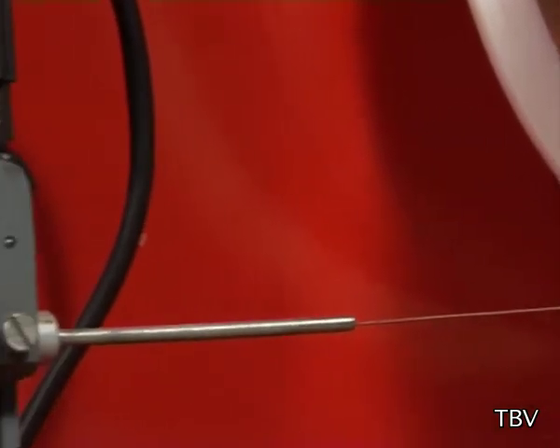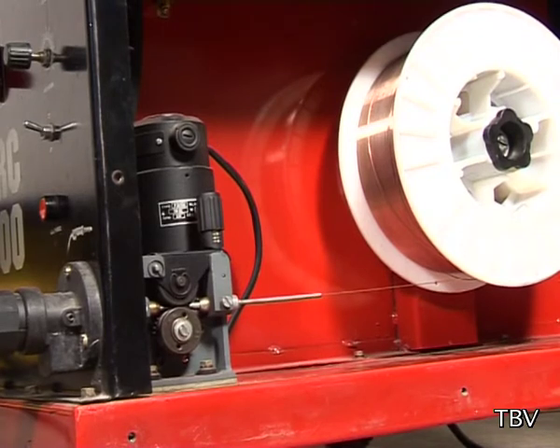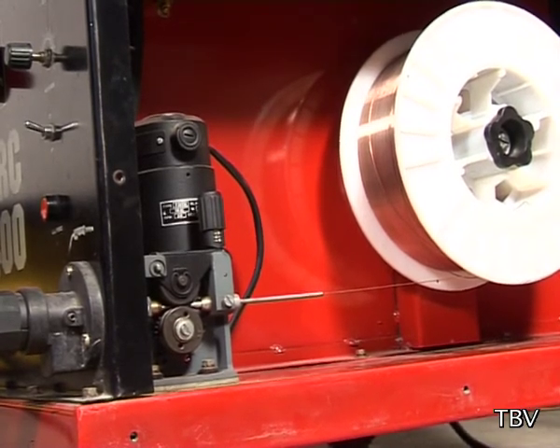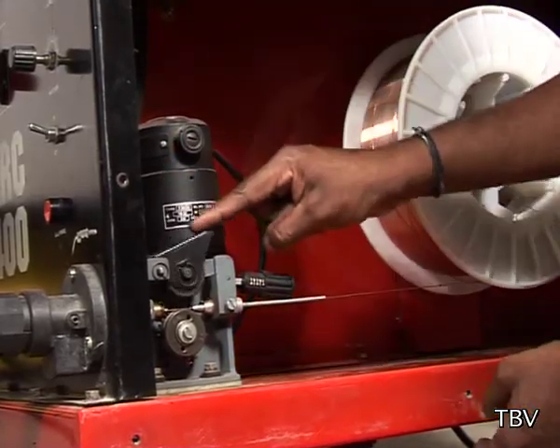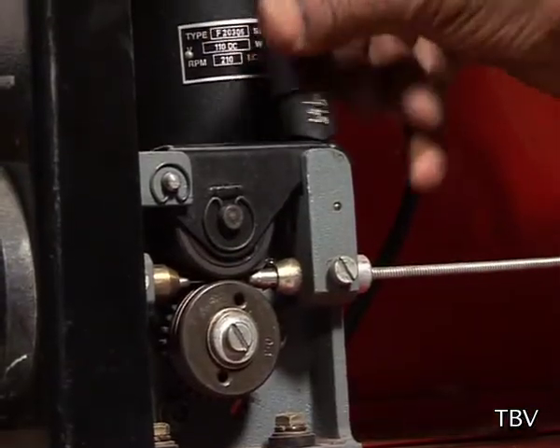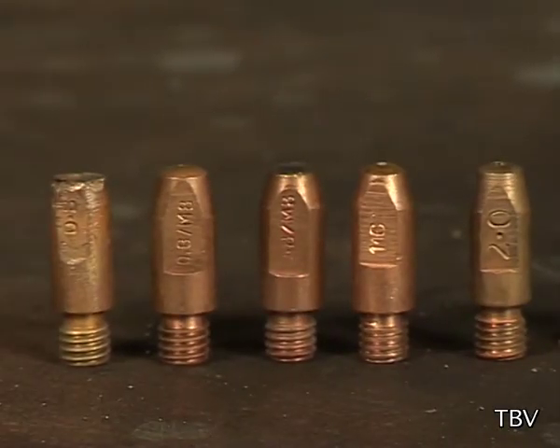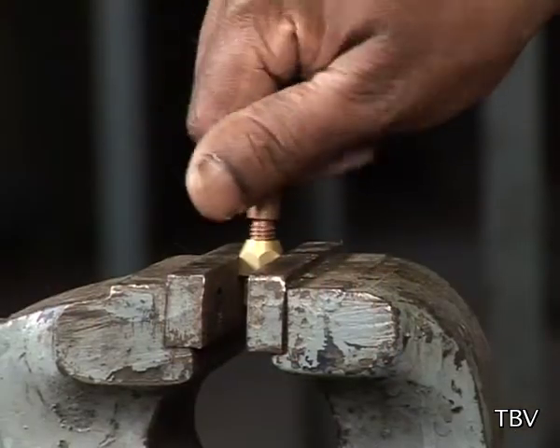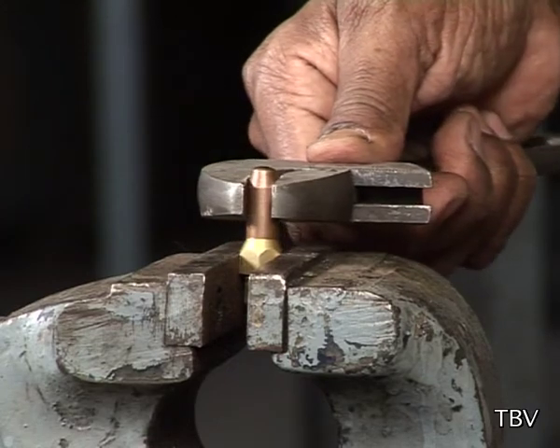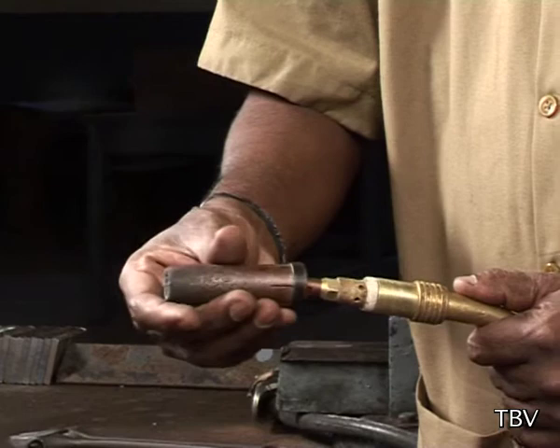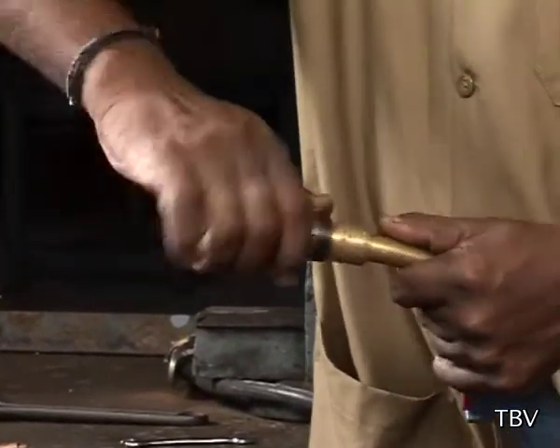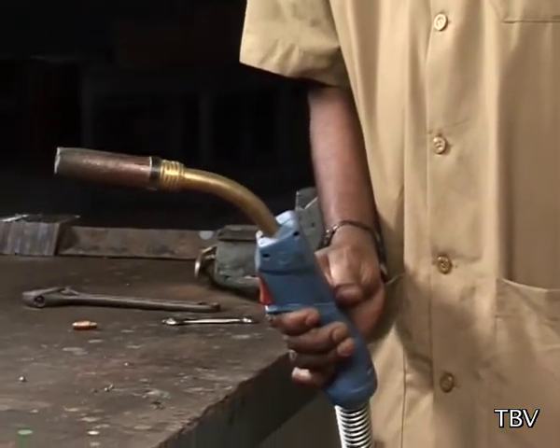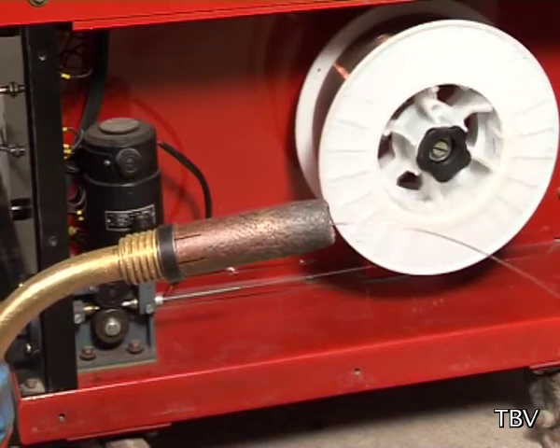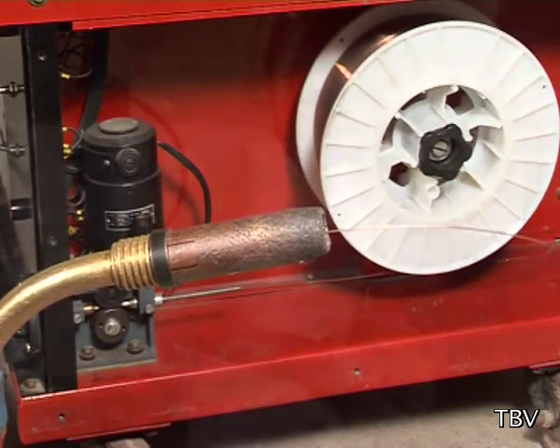Do not tighten the copper-coated mild steel or CCMS wire too hard. Otherwise, there will be a possibility of the copper coating to peel off from the wire. Now, lock the roller groove. Set up a tip matching the welding wire size. Firmly tighten the tip. Check if the tip attached to the welding torch matches the guide or roller groove and also the wire size. Switch on the welding machine.